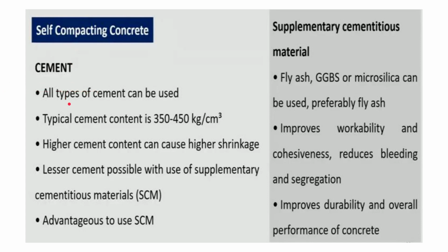Here it has been found that basically all types of cement can be used, and it should have a content between 350 to 450 kg per cubic meter. So per cubic meter of concrete, an amount of 350 to 450 kg should be used. Higher cement content can cause a higher amount of shrinkage. That has to be kept in mind, because plastic shrinkage and other parameters can come into play because of the voids due to evaporation of the capillary pore water.